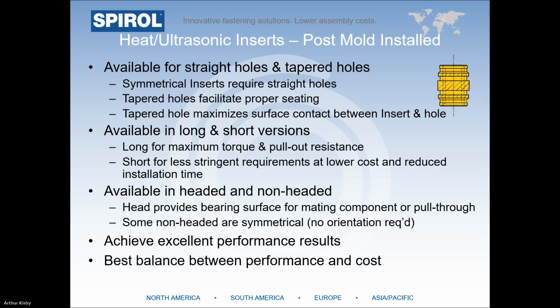A symmetrical insert design eliminates orientation issues during the installation process. You can achieve excellent performance results with heat ultrasonic inserts provided they are used in the proper hole size and sufficient wall thickness around the insert, and they're installed with proper melting of the plastic to fill the voids of the insert. Heat ultrasonic inserts generally provide the best balance between performance and cost.